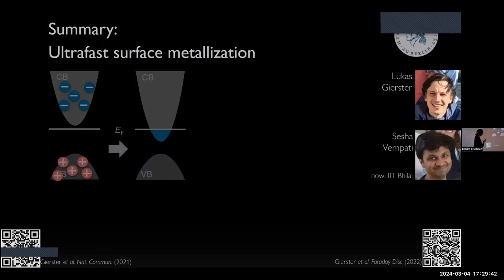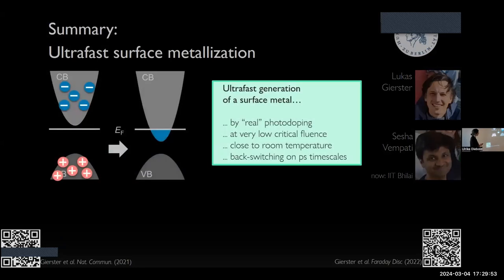So I showed you that we can metallize the zinc oxide surface by photo excitation. The main characters of this work were Lukas Gierster and Sesha Vempati. In summary, we do real photo doping, the real analog to photo doping, which is also reflected in this critical behavior. We can do this close to room temperature, and we have this back switching on picosecond time scales. So we believe that this is actually of technological relevance, what we've discovered here.